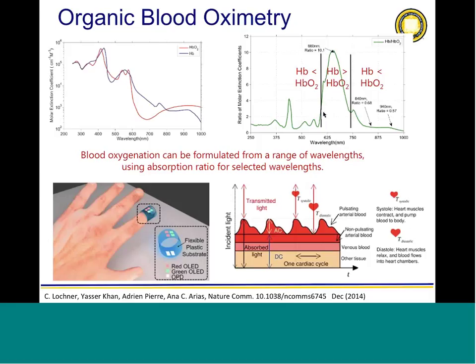So that's the first step in performing this measurement. You have to pick the wavelengths that will give you that ratio, or the highest possible. And then you compare the ratios that you get at two wavelengths. For the electrical engineers here, when you are measuring pulse oxygenation, you have a pulse going, and that's the signal that you want to pick up. But the light is also going through bone, through tissue, through blood that's not pulsating, and all that contributes to a DC signal in your measurement that is quite large. Then you have this little AC signal oscillating on top of the DC signal, which carries the pulse information. So for pulse oximetry, you have to pick up this AC signal.